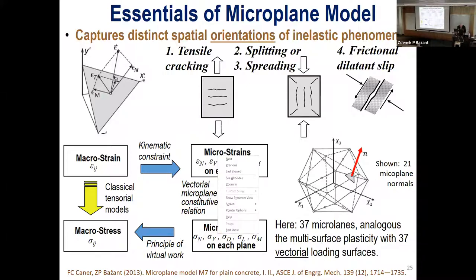Now the algorithm: you go from this continuum strain or macro strain by kinematic constraint to the micro strain. And then you must have a vector micro-elastic stress-strain equation based on these physical ideas. You get micro stress, and these need to be assembled into macroscopic stress. That's done variationally by the principle of virtual work. That requires integration over all spatial directions or the unit sphere, and that has to be done by optimal Gaussian integration. The minimum number necessary is 21 microplanes in discrete form, which are normal to these points here. But in practice, we use 37. It's of course more computational work. Instead of going straight by the classical tensor model, we go through the micro. But for large computer programs, it makes no difference.